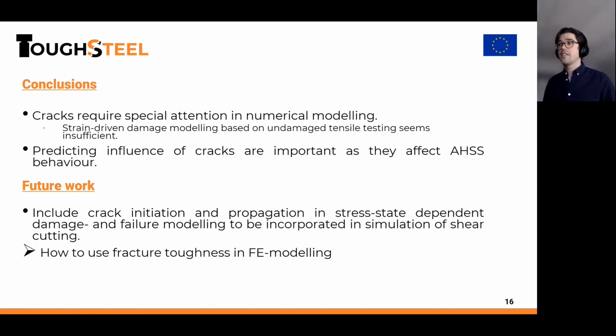And today you find several numerical methods that are specialized in crack tip modeling. There are various ways of constructing your mesh in order to model crack tip plasticity, and you have XFEM that is shown to be efficient in modeling of crack propagation, and you also have other meshless methods such as peridynamics that are suitable for this. However, few of these match the versatility and the user friendliness of the GISSMO model, which is a problem when you are modeling, for instance, shear cutting. We have a damage model that needs to handle a large range of failure modes and failure